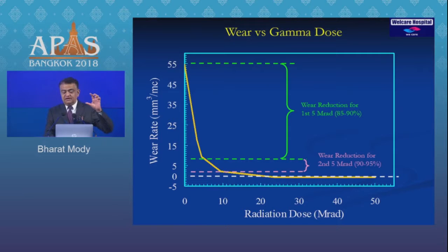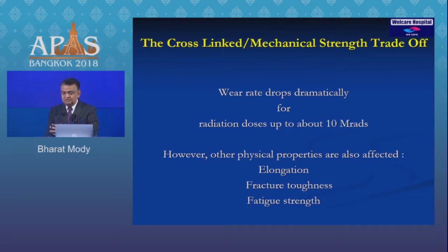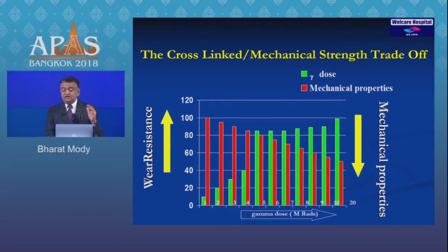The first 85 to 90% of cross-linking is achieved when you expose the poly to 5 megarad of radiation. Another 5 megarad of radiation will increase the wear resistance by 90 to 95%. The problem is that whilst the wear rate drops dramatically up to 10 megarads, other properties are also affected. For example, the elongation, fracture fatigue, and toughness. So in other words, there is a mechanical versus behavioral sort of wear resistance trade-off here. The increase in wear resistance is also associated with a decrease in the mechanical properties of your poly.